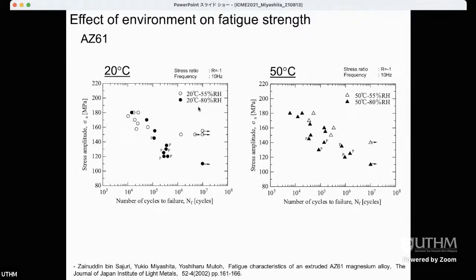If we carried out a fatigue test at high humidity condition, especially for the low applied stress and longer fatigue life region, fatigue strength decreases like this at high humidity condition. And we also put the P mark. This means fatigue crack initiated from corrosion.